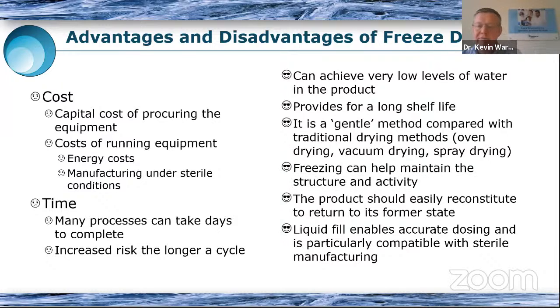And this can provide for long shelf life, because with many products, the reason we're drying is because water is a problem, and hydrolytic reactions are often the basis for degradation. And so if we can achieve very low levels of water, then we have a long shelf life. We could also consider it a gentle method compared with the other drying methods, which often use elevated temperatures. Here in freeze drying, of course, we're starting off by removing heat from the product. And so even if we consider traditional Arrhenius kinetics or Williams-Landel-Ferry kinetics of degradation, the first thing we do is to remove heat. And that in itself can be a good thing for stabilizing liquid products.